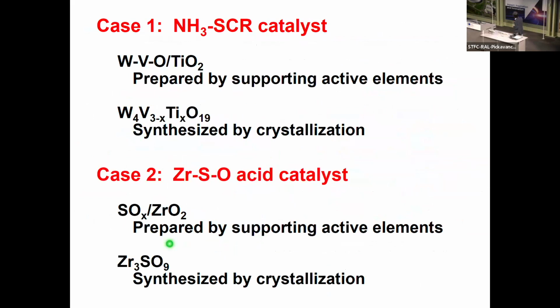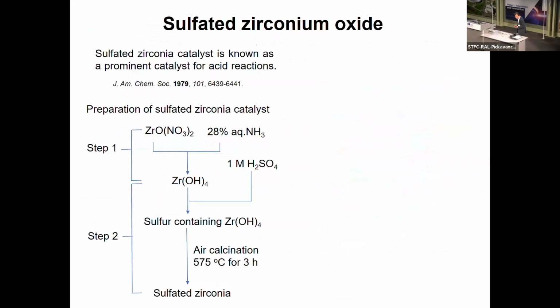Zirconium sulfate species. As I said at the beginning, this catalyst was developed quite a long time ago, in 1979, by Japanese people. The preparation process is shown here. You first make zirconium hydroxide, which can be formed as a precipitate, and then you add sulfuric acid. Then you dry it and calcine it at a high temperature. Calcination is very important. Without calcination, you cannot get any solid acidity. This is very important. I have to remind you.